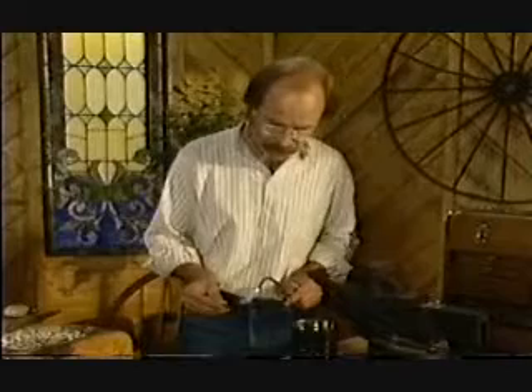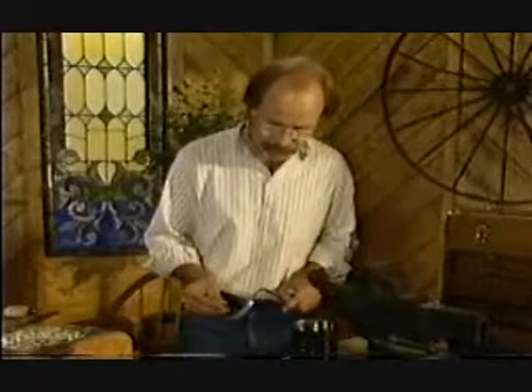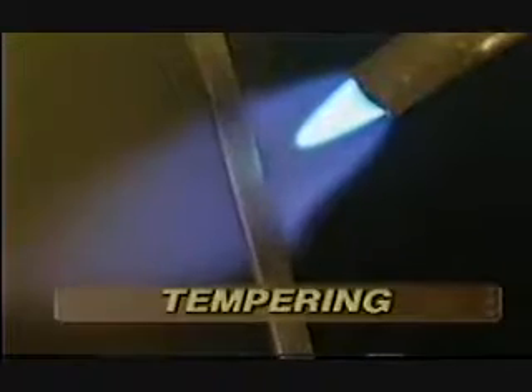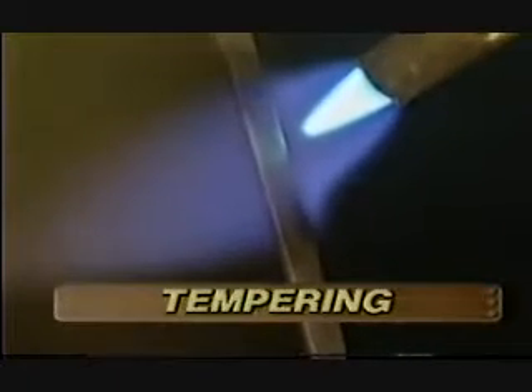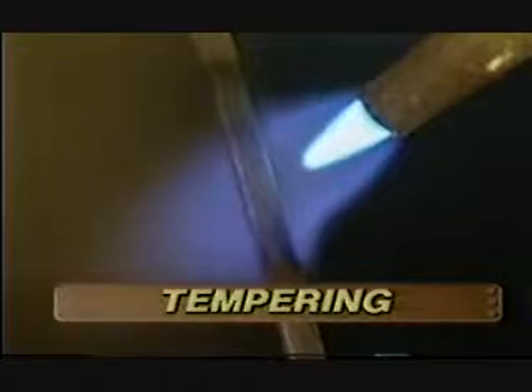Nothing's going to happen for a few seconds, and then you're going to see a rainbow of color. There it is. You'll see blue in the center. Next to it is plum, followed by brown, followed by a straw or bronzy yellow. It's that bronzy yellow that I'm going to watch. As I keep the torch here, that color is going to crawl toward the tip. It's also crawling up the handle, but I'm not too worried about that. I'm watching the one that's going toward the tip. And when the straw gets to the tip, then again, moving quickly, I'll quench the tool.